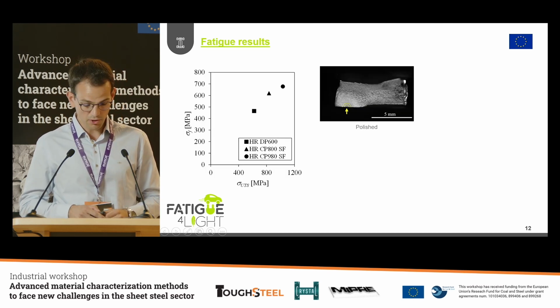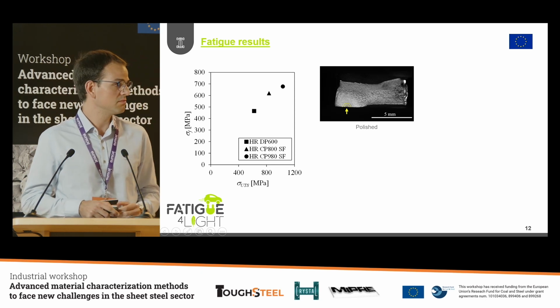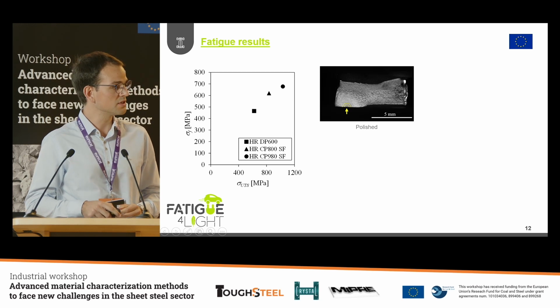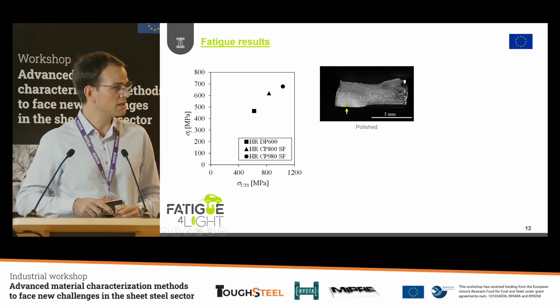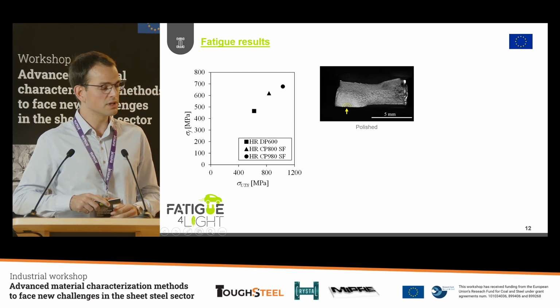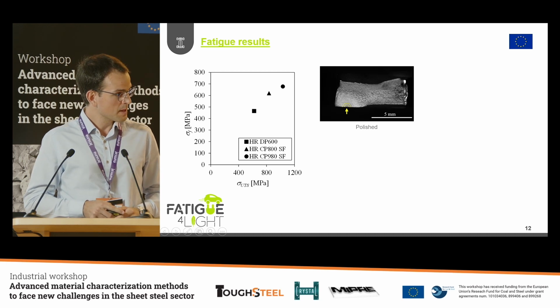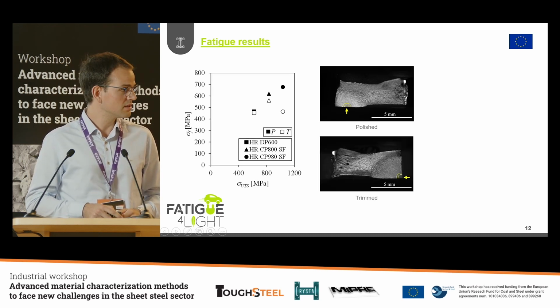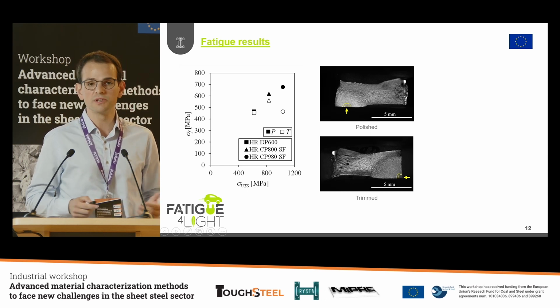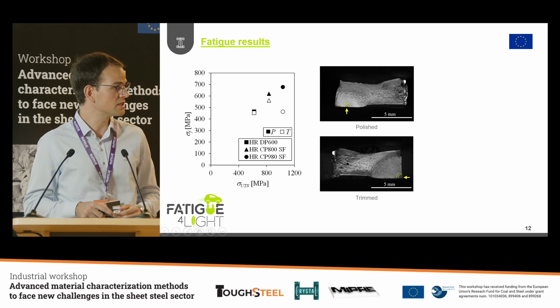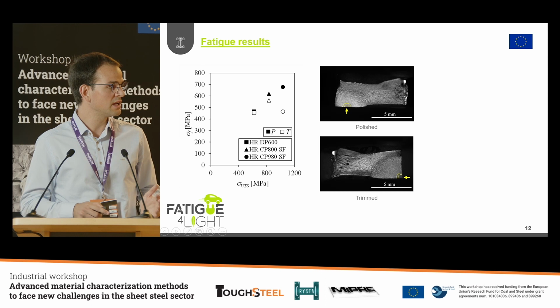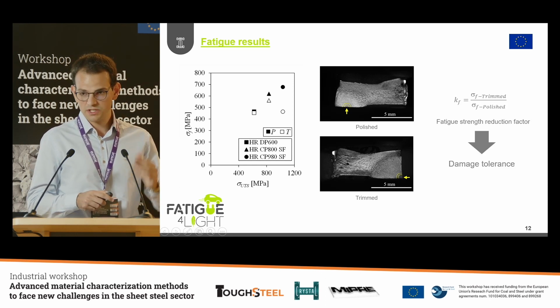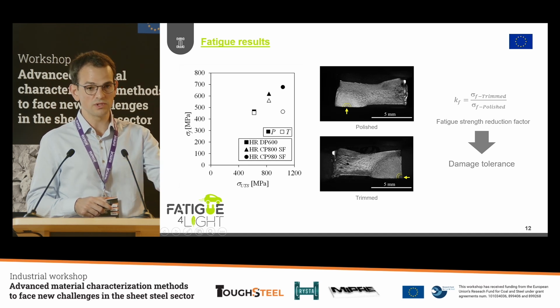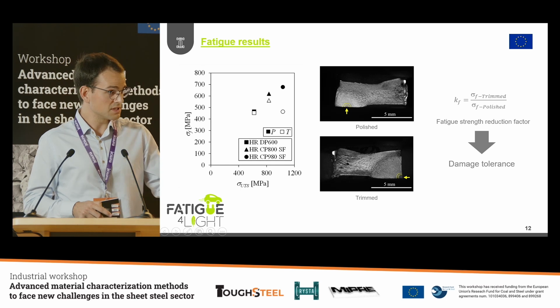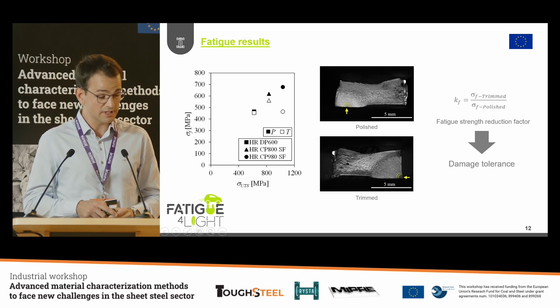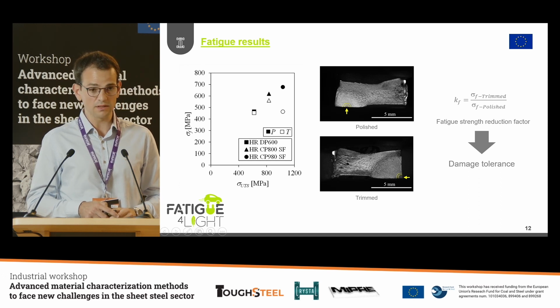So here, if we plot this fatigue data for the condition without defects, so the perfect condition, against the tensile strength, what we can see is what we saw at the beginning of the presentation. If we increase the tensile strength of the material, we increase the fatigue resistance of the material. But when we have a defect, this behavior is completely different. And for some materials, we have some fatigue reduction. So for instance, for the DP600, the fatigue resistance is almost maintained, but for the other materials, like the CP, it's reduced. Such fatigue reduction can be quantified by using this fatigue strength reduction factor, that is simply the relation between the fatigue resistance of the polished specimens and the trimmed ones.